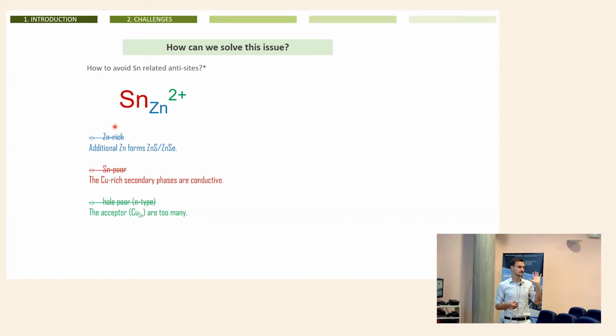So our material is copper 2, tin 1, zinc 1, selenium 4, for example, in a stoichiometric condition. But if you prepare a zinc-rich compound with, for example, copper 2, tin 1, zinc 1.2, selenium 4, then you can try to avoid the formation of this kind of defect. The problem is that when you increase the zinc concentration and you are going out of stoichiometric condition, zinc selenide and zinc sulfide tend to be formed, are very stable phases, and normally also deteriorate the properties of your devices.